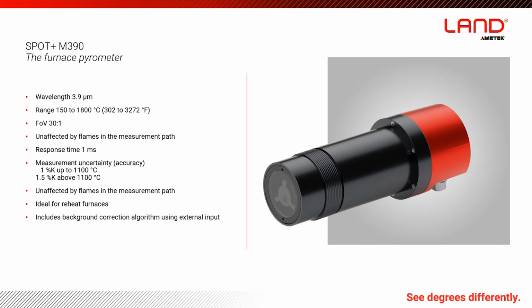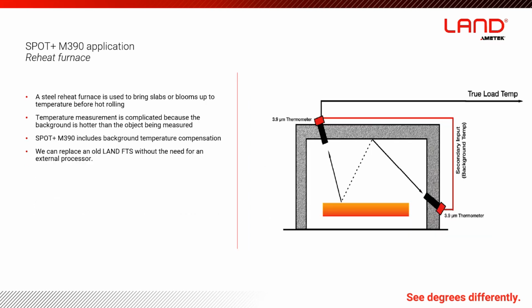Measurement uncertainty up to 1100 Celsius, we've got 1% Kelvin, a little bit worse than that at the highest temperatures. And it's really intended for reheat furnaces and applications where you're looking at an object within a furnace that may be surrounded by flames and certainly by hot gases. And it's got a built-in background correction algorithm using an external input. All of the pyrometers I'm going to talk about today have got this algorithm, but it's particularly useful for the M390 because of its furnace application.